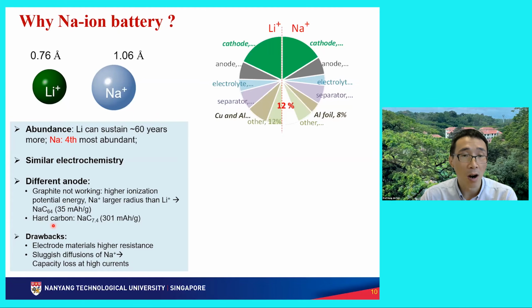So people are using hard carbon. This is also the material used for commercial sodium batteries, hard carbons. The capacity is 300 milliampere hour per gram, which is comparable to graphite for lithium. But the drawback is, as I mentioned just now, the sluggish diffusion of sodium ions because the radius is larger. So there is also capacity loss at high current. Why this consequence?